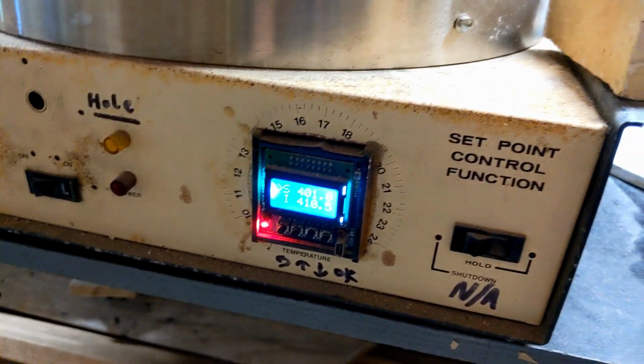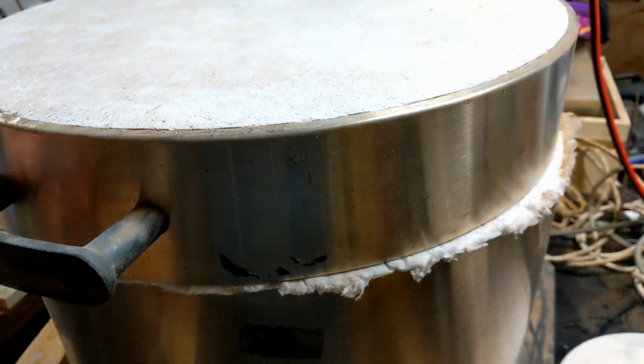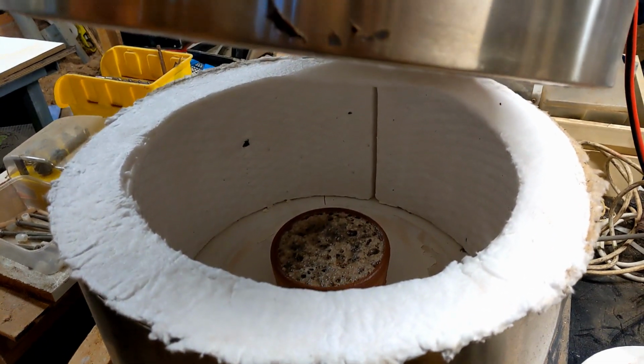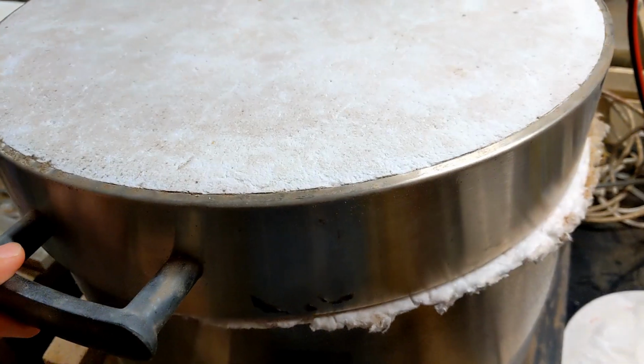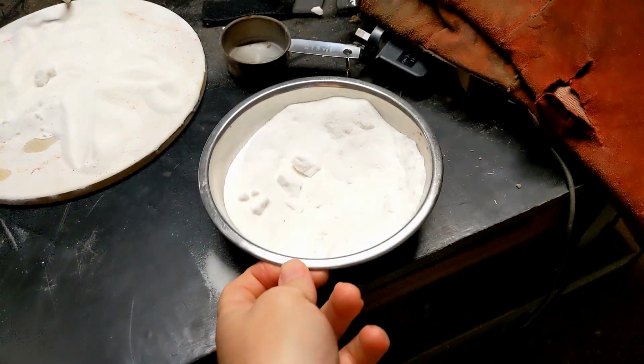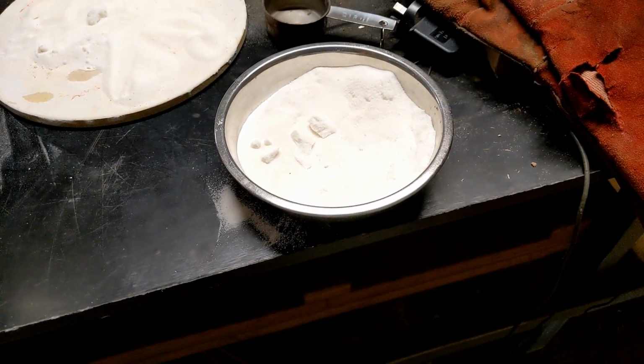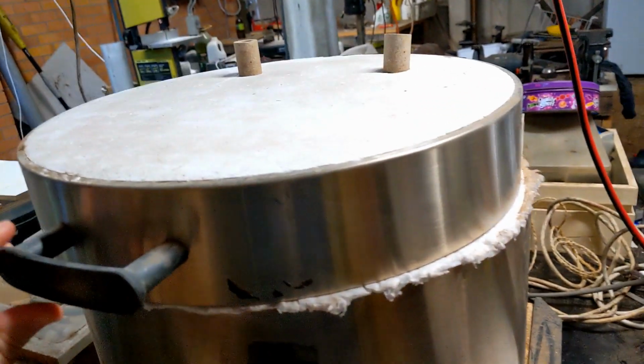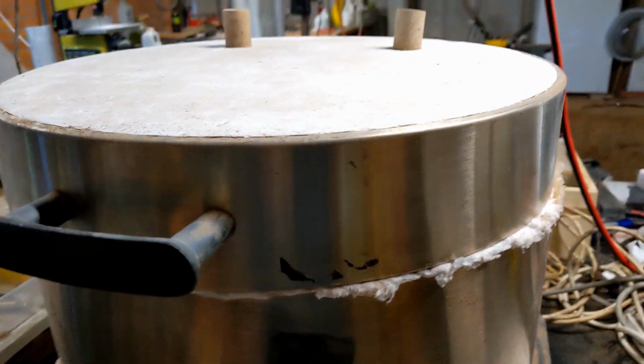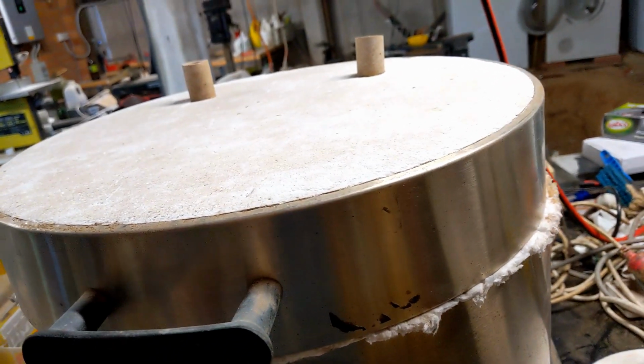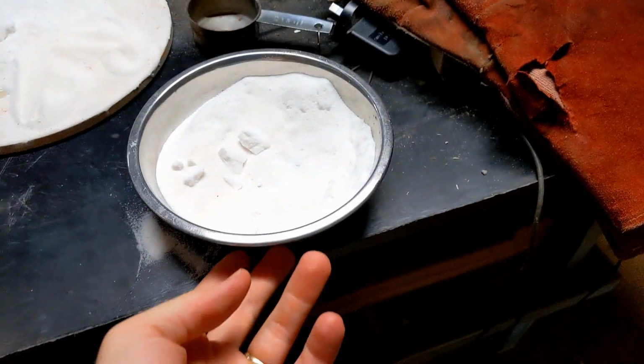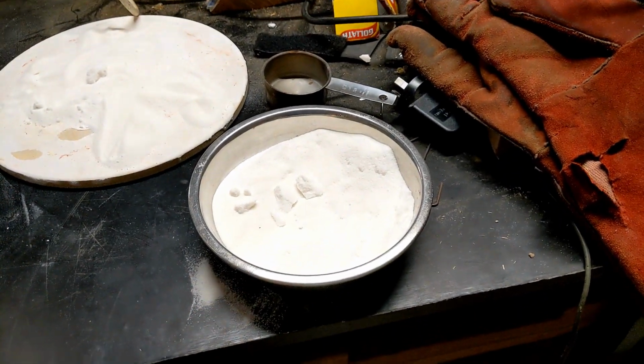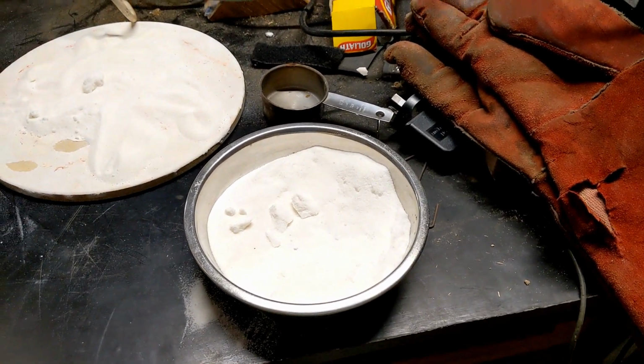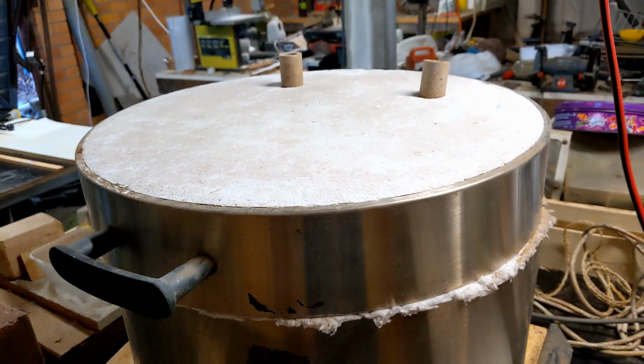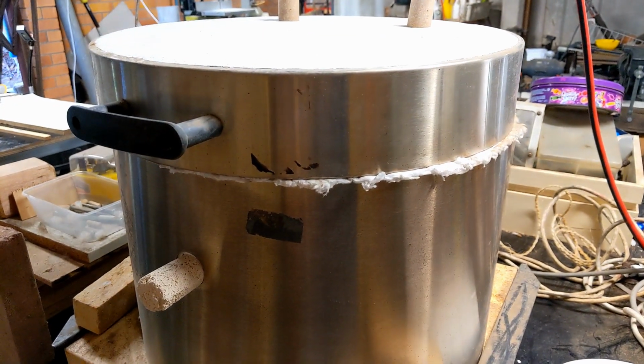It's almost finished its period at 400 degrees Celsius with the glass slug in molten potassium nitrate. So it's developed this lovely sort of bubbly brown texture. That's what it looks like fresh. And I've melted potassium nitrate before and it just goes clear. So I'm not sure why it's all bubbly and brown. I wonder if it's sort of eating the glaze on the terracotta pot I've got it in. Maybe. I decided against the stainless one for fear of it just explosively oxidizing when it gets up to temperature. But, see how it goes. Bye bye.